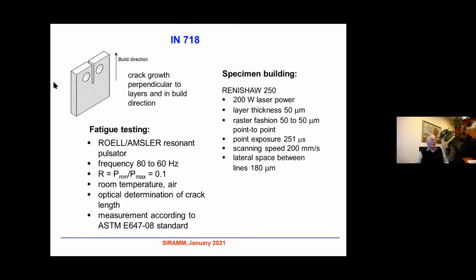Again, we have prepared such CT specimens. In this case, we studied only crack propagation in this direction, the build direction. Specimens were prepared on a Renishaw machine with 200-watt laser power. Layer thickness was 50 microns. Raster fashion was 50 by 50 microns, point to point. The point exposure was 251 microseconds. Scanning speed 200 millimeters per second. Lateral space between lines 180 microns. You can see that there are many parameters which can be changed.